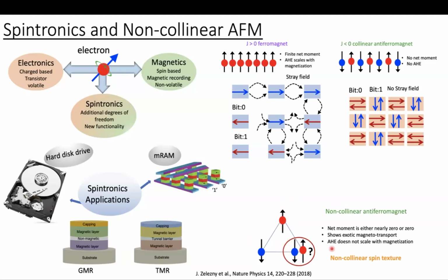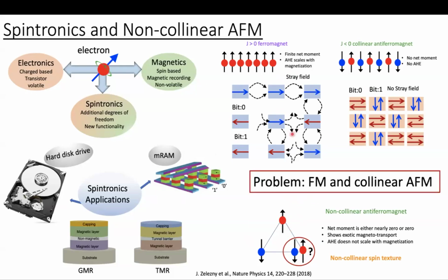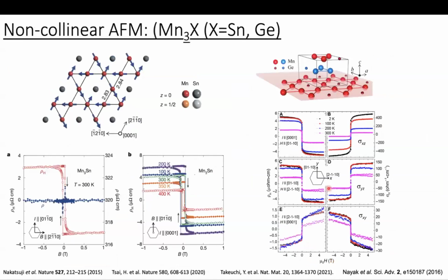Take the anomalous Hall effect, let's say. Usually in ferromagnet, it scales with the magnetization, whereas in non-collinear antiferromagnet, it doesn't scale with the magnetization, as the magnetization is nearly zero and the origin is different. So right now, the existing problem is with ferromagnet and collinear antiferromagnet. And now let's see how non-collinear antiferromagnet can be useful to solve this problem.